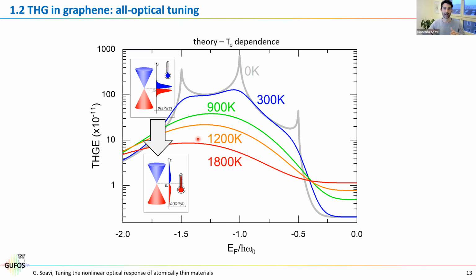Because instead of having something sharp, it's very similar to, even if you look at the absorption or photoluminescence in a TMD at cryogenic temperature or at room temperature. At room temperature, you have the thermal broadening, and basically you have the same oscillator strengths, but distributed on a larger wavelength region. If you now go to cryogenic temperatures and you narrow down because you don't have the thermal broadening anymore, the maximum is much higher, but just on a narrow linewidth. But at the end, if you take the integral, it must be the same. Yeah. Okay, I see now. Yeah.